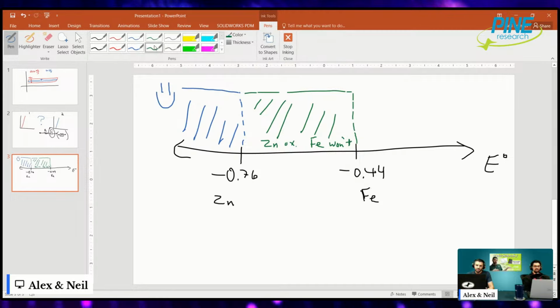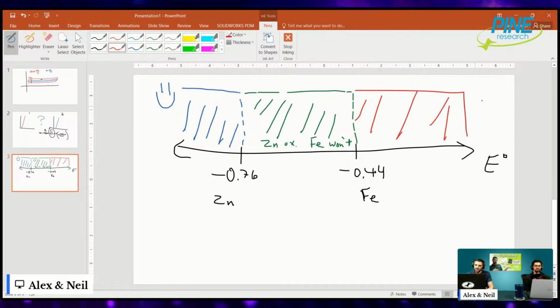And in this region, everything, we're sad. Everything is oxidizing and rusting and dying. Both of them will. But it's this middle region here, which is why this works. Because in this potential region between basically minus 0.76 and minus 0.44, zinc can oxidize, but iron can't. And I say can't, it's not exactly the case, but I'm just being simplistic here. The iron will really only do the oxidation mechanism if we go positive of its potential.